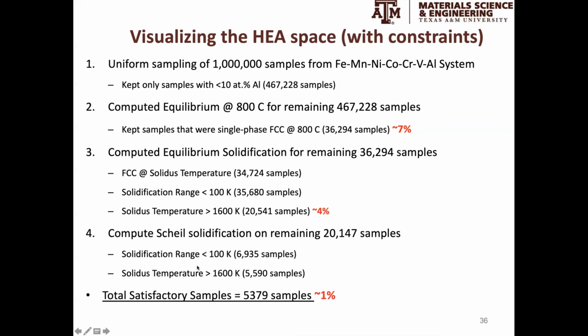If we consider Scheil solidification, we arrive at the conclusion that the total percentage of alloys in this vast alloy space—out of 1 million samples that we considered—after applying all these constraints, we find that only about 1% of the total space is feasible. So clearly, 1% of a pretty large space is still pretty large.